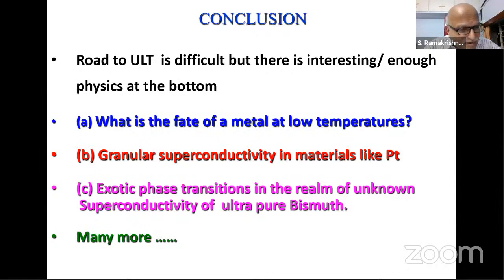So all these high pressure people, that's what they are trying to do. They are taking hydrides. Metallic hydrogen is supposed to have a Debye temperature of the order of 1,000. So it all started with that. The theory said if you make metallic hydrogen under pressure, it will become a superconductor at room temperature. Initially they tried to squeeze hydrogen gas into a solid, but unfortunately it was metastable and so forth, so it was not possible. The whole thing was abandoned in the 70s and late 80s.